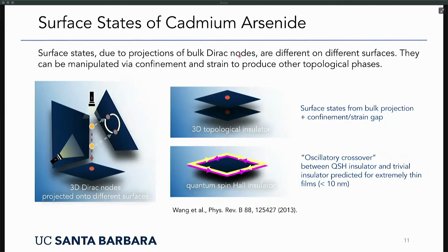So the interesting thing about these topological materials is that there's what people call a bulk boundary correspondence, and that's illustrated here in a very cartoonish way. So I've illustrated here the bulk Dirac nodes as these orange dots, and depending how they project on the surfaces, you get different types of surface states. So except for the 001 surface, where these two Dirac nodes line up along the 001 direction and project on a point on the surface, all the other surfaces project on separate points in the Brillouin zone of the surfaces. And what you get in these cases are these Fermi arc type of surface states that connect the projections of these bulk Dirac nodes. Okay, so there are surface states on all the surfaces, but the 001 surface, which I will talk about later, is a little different. It does not have these Fermi arc structures.